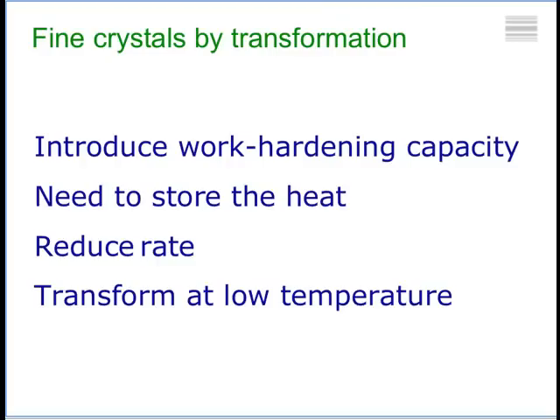First of all, let me just summarize the things that we need to do to produce a successful nanocrystalline material. We need to introduce a work hardening capacity, because without that, you will get plastic instabilities. We need to store the heat of transformation inside the material. We must reduce the rate of transformation because that allows time for that heat to dissipate. And transforming at a low temperature is always a good thing because it reduces the scale of the structure. Let me go to this point here, which is how do we store heat?